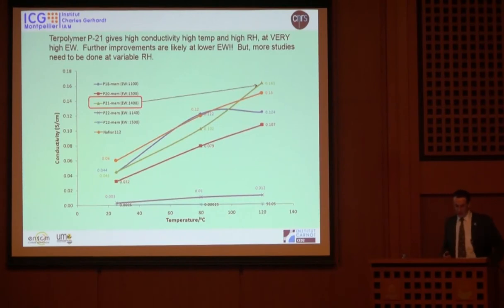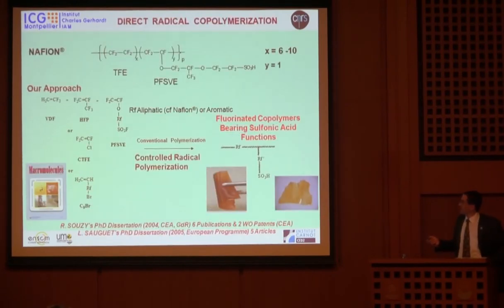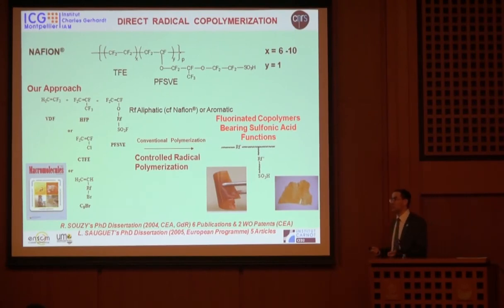What we try to do in the lab is to mimic Nafion with vinylidene fluoride. We work a lot on vinylidene fluoride. I told you that TFE, tetrafluoroethylene, is explosive, so I took the responsibility not to use any TFE in the lab. And we tried copolymerization or polymerization with hexafluoropropylene and this monomer to make some new membranes, even using chlorotrifluoroethylene or this kind of brominated compound, which enables cross-linking by the bromine and by radicals.